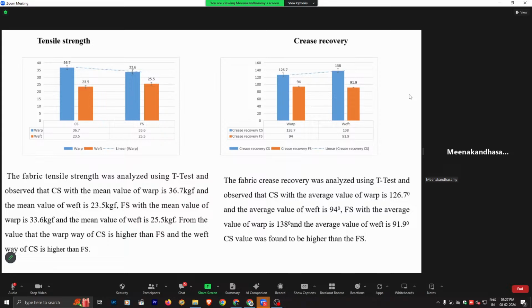Next one, crease recovery. The fabric crease recovery was analyzed using a t-test. The control sample had an average warp value of 126.7 degrees and an average weft value of 94 degrees. The finished sample had an average warp value of 138 degrees and an average weft value of 91.9 degrees. The control sample value is found to be higher than the finished sample.